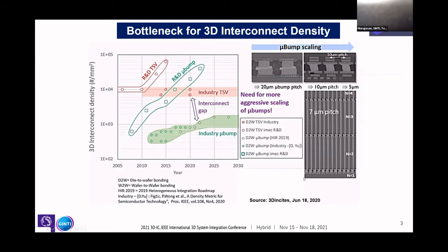These are some of the micro bump bonding technologies, with bump and bumpless, that is copper to copper direct or hybrid bonding. This is some of the work we have carried out at Tohoku University. From the 10 micrometer copper-tin, a typical one, we were able to achieve even a couple of micron to 4 to 5 micron pitch for indium-copper micro bump. Sony has, 5-6 years back, already shown that the TSV pitch itself is less than a couple of microns. But this is talking about only my TSV pitch. When you are going to do your bonding, you are facing only 14 micrometer or something. So the question arises: from the moment you bond your stacked die, the bonding pitch we are not able to reduce as much as we think or have to.